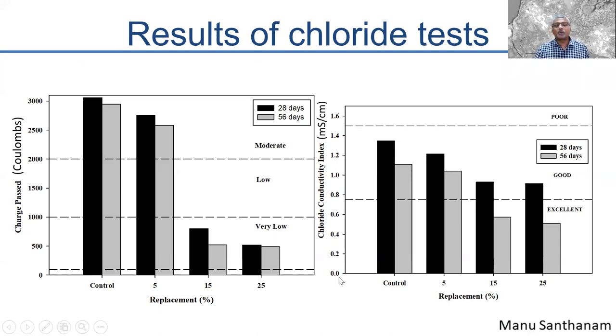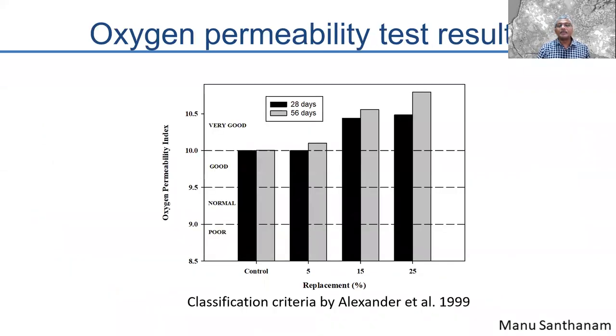Similarly, the chloride conductivity index, which is another index test done as per a South African method, shows clearly that when you replace cement with bagasse ash, you see a decline in conductivity. Lower conductivity means better durability. The oxygen permeability index is plotted here, which is basically the negative logarithm of the permeability coefficient. If the permeability coefficient is very low, your permeability index value is going to be high. So the higher the value, the better the concrete.